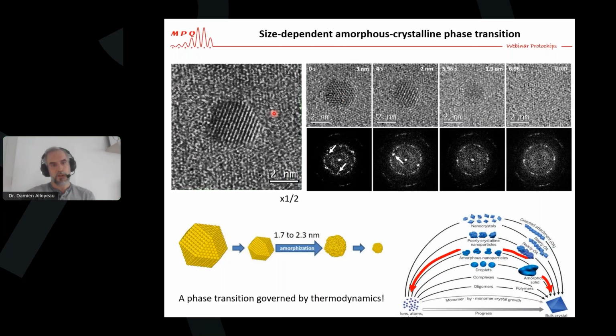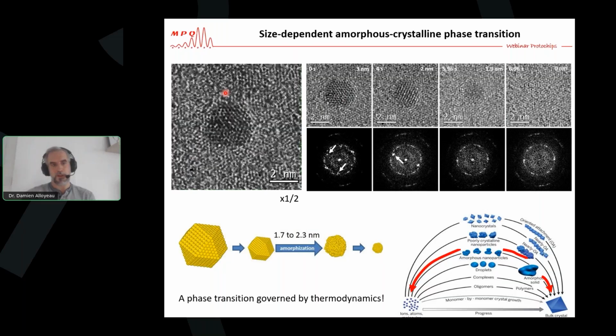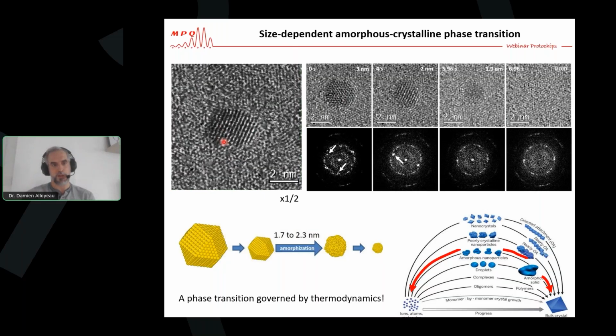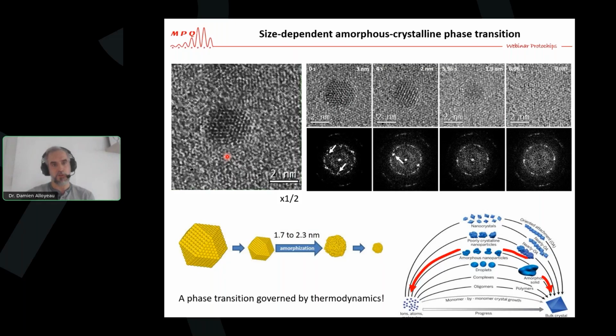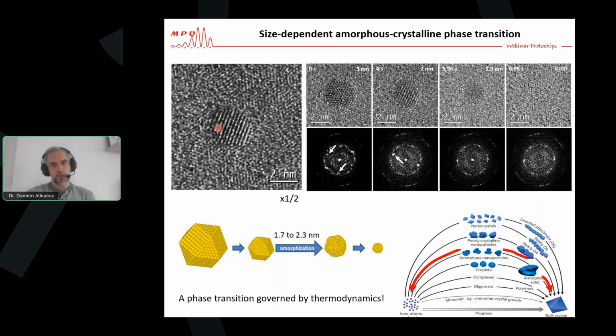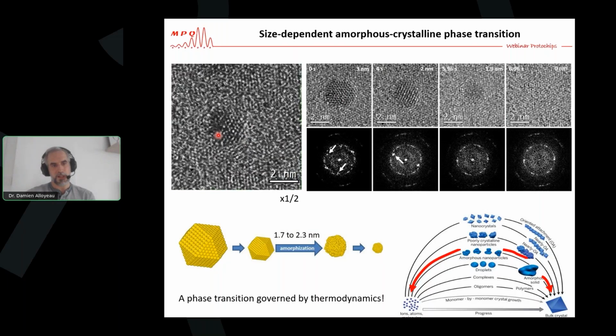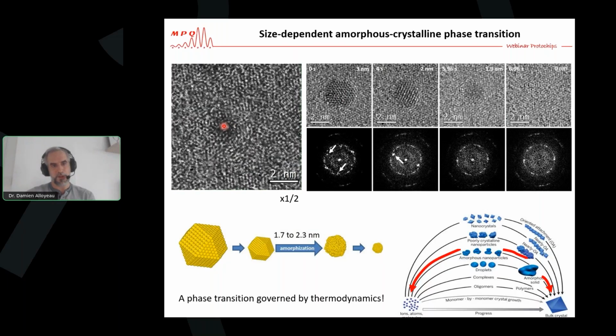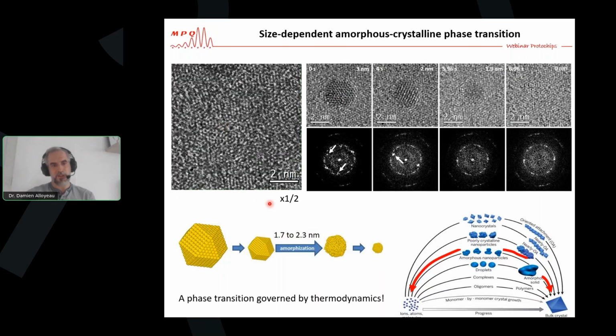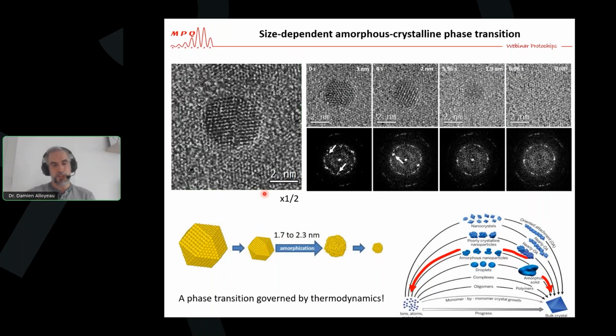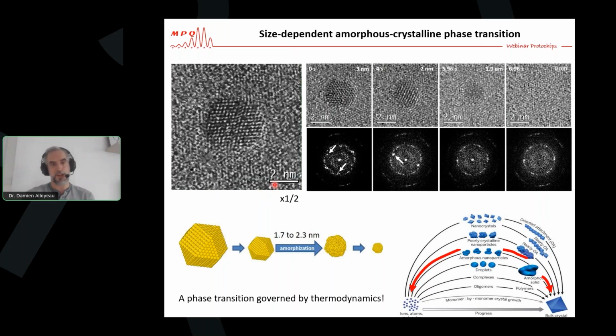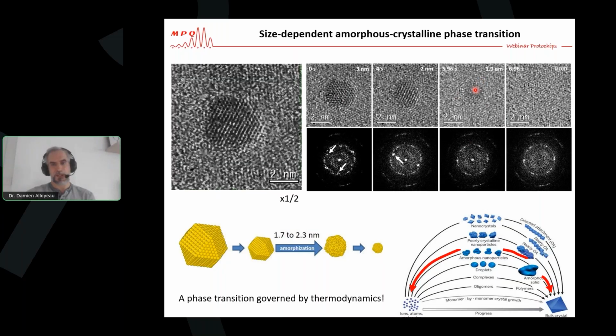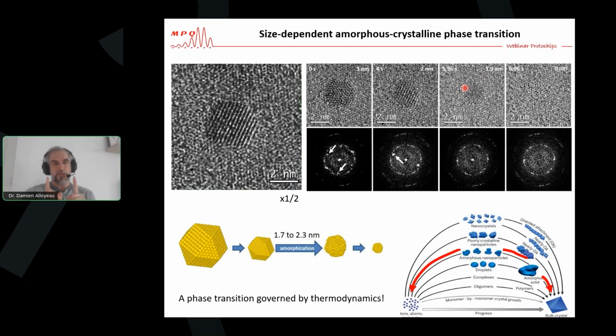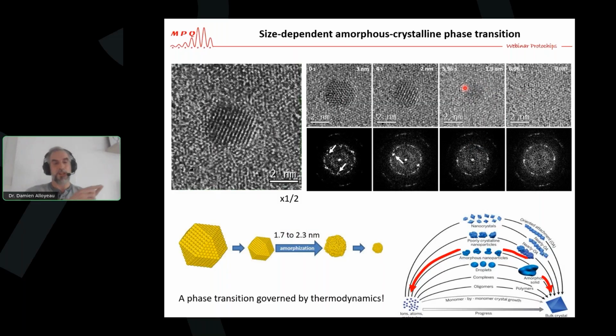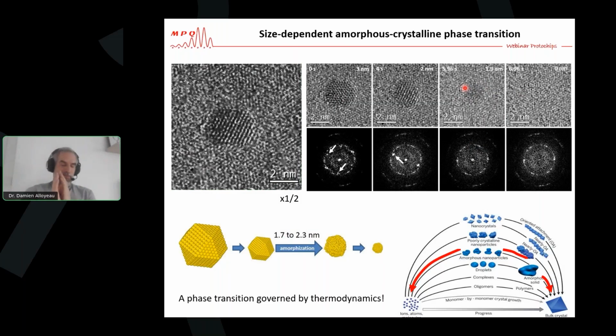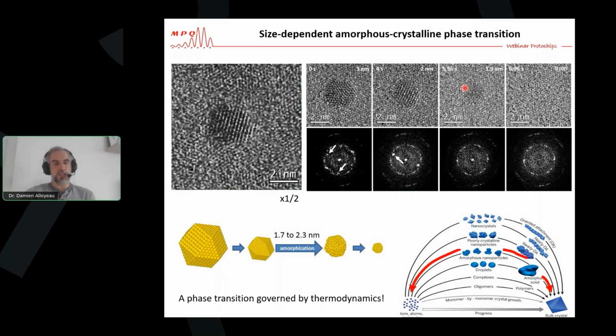And here you see that when you have no ligand, this etching is isotropic. But at some point, when the particles go below 2.3 nanometer, you see the crystal planes disappear, and then between 1.7 and 2 nanometer, it's actually switching very rapidly from the crystalline phase to the amorphous phase. And when it's below 1.7 nanometer, the nanoparticles are systematically amorphous. So the fact that you have this phase transition both ways, during the growth or the etching of the nanostructure, clearly indicates that this phase transition is governed by thermodynamics.